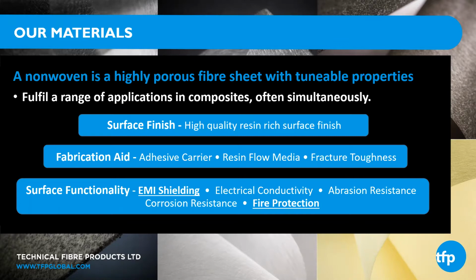What people tend to focus on and think about with lightweight non-wovens is surface finish. The application of a lightweight glass or polyester veil to give a resin-rich surface layer. They also find widespread application as fabrication aids, such as adhesive carriers, resin flow media, in fracture toughness. But what really excites me is surface functionality. The ability to tune the product through selection of the fiber and the way the fiber is incorporated into the veil, and potentially other additives to give a higher level of functionality. So as well as the surface finish, to be able to give a simple drop-in lightweight veil that offers EMI shielding, electrical conductivity, abrasion resistance, corrosion resistance, and fire protection. And it's really the EMI shielding and fire protection that we're interested in today. Next slide, please.